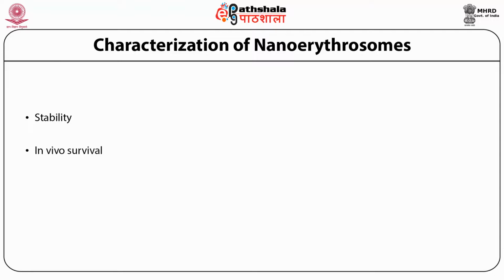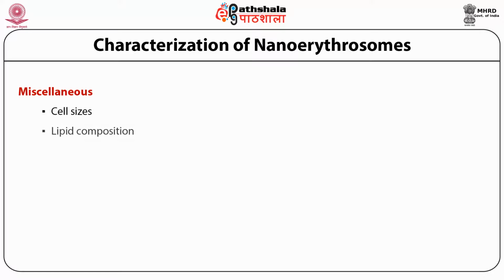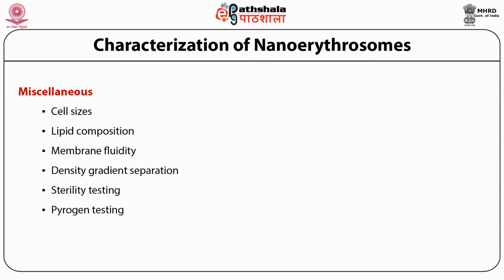Next parameter is in vivo survival. A number of procedures are suggested to evaluate in vivo survival period, such as radio tagging of RBCs by 51 chromium or fluorescent marker like fluorescein isothiocyanate or encapsulation of 14 carbon sucrose or gentamicin. The endurance of tagged cell is determined by flow cytometry. Other than the tests which have been discussed earlier, there are more tests. The nanoerythrosomes can be characterized by cell sizes, lipid composition, membrane fluidity, density gradient separation, sterility testing, pyrogen testing, animal toxicity, because these RBCs have to undergo into the parenteral system.